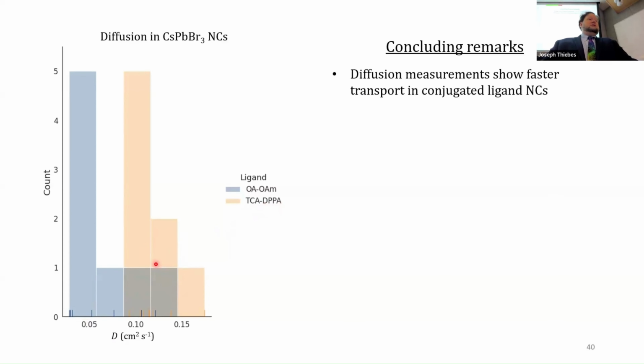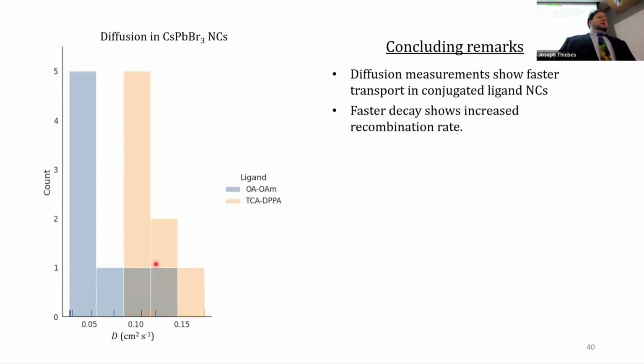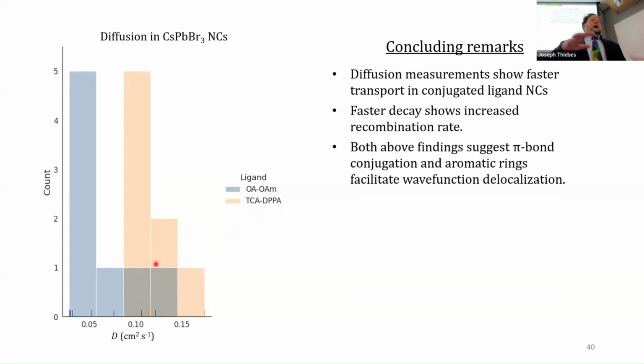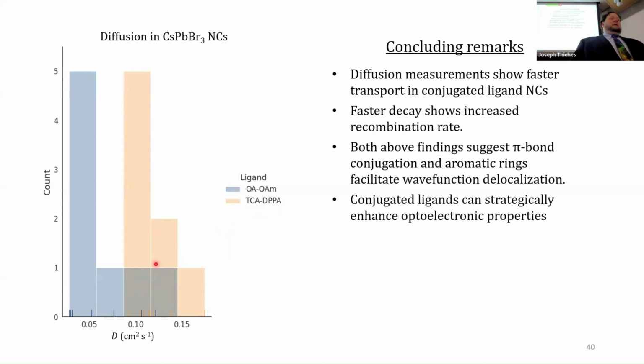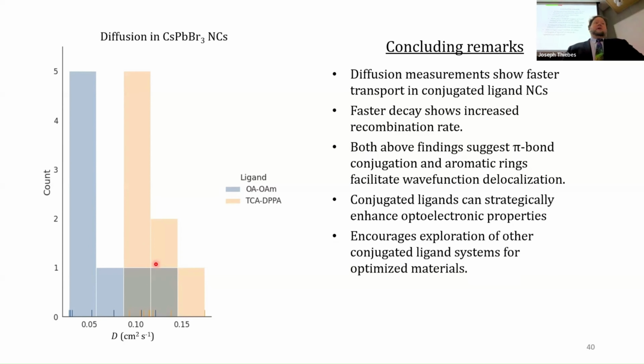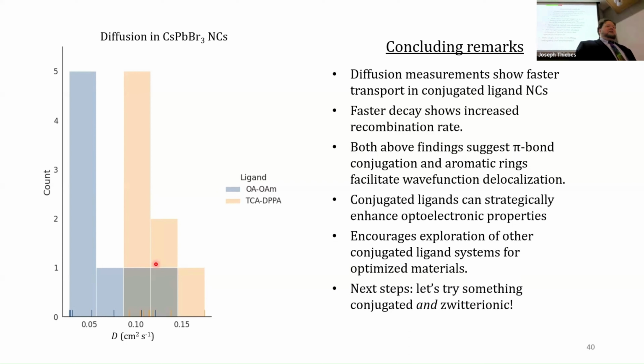The diffusion measurements do consistently show faster transport in the conjugated ligand nanocrystals. The faster decay shows increased recombination rate, which we'd expect. Both of the above findings suggest that we've got pi bond conjugation and aromatic rings facilitating that wave function delocalization. And the conjugated ligands, for engineers, can be used to strategically enhance optoelectronic properties. And that encourages exploration of other conjugated ligand systems for optimized materials. And I've got ideas, by the way. So for the next step, we could try something that's conjugated and zwitterionic, because that would have the ability to use a bidentate mechanism to connect to the nanocrystal.